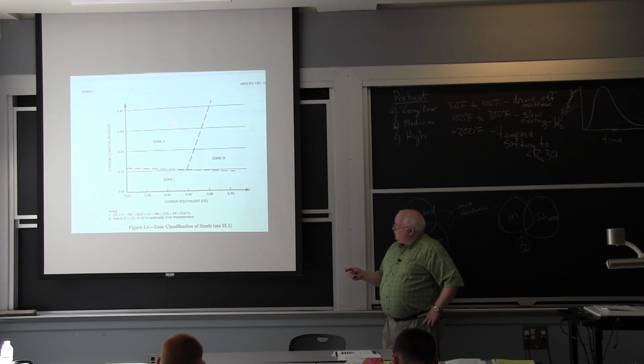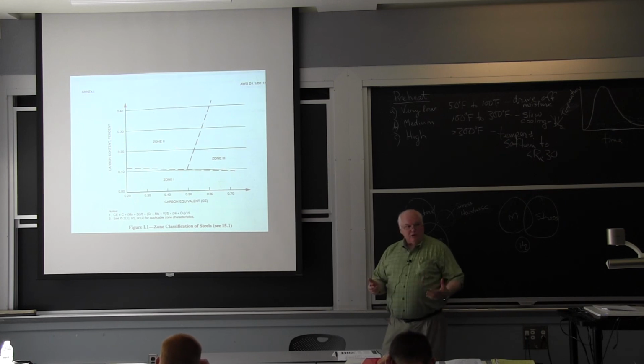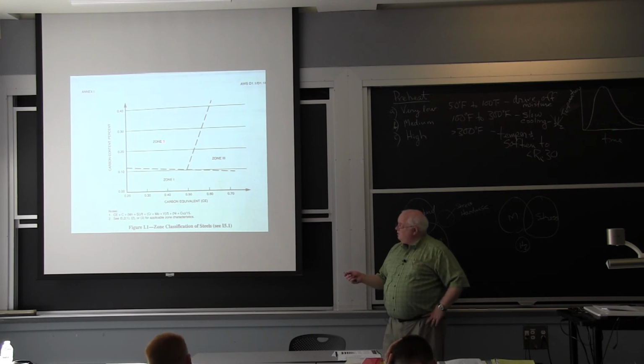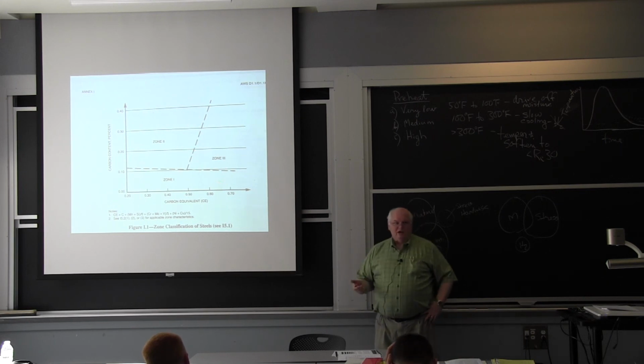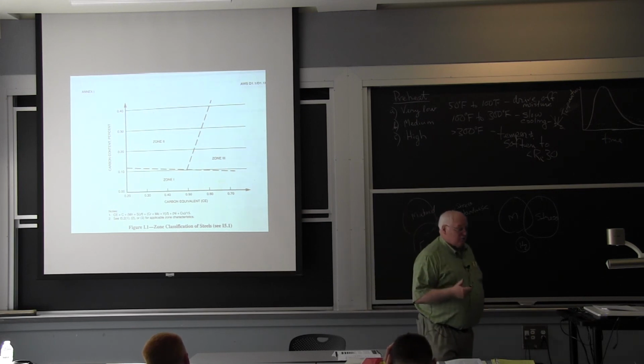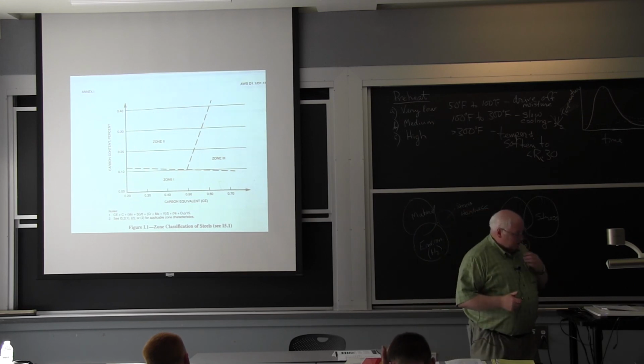The good thing about HY80 is it's right about in here, in zone 2. You have to use some preheat. Down here in zone 1, you're going to find you don't need preheat at all in most cases. HY80 is right in here. HY100, higher strength, same carbon, is getting right up against this line. And zone 3, high depth of hardening, high potential hardness, these are the ones that are going to take a lot of preheat.